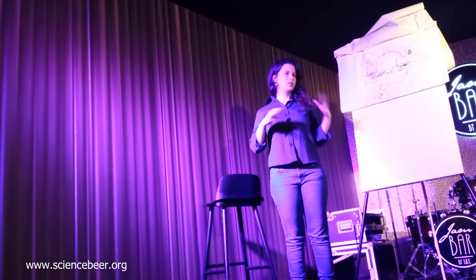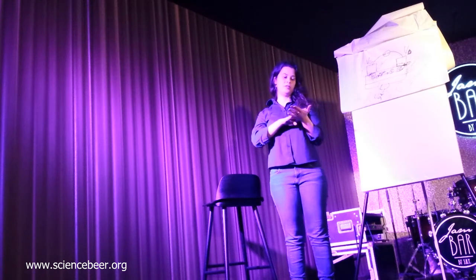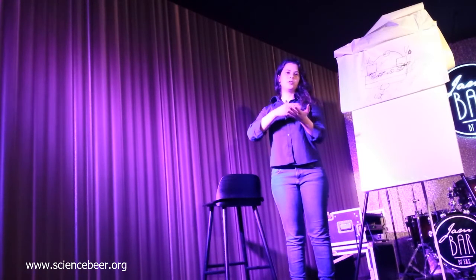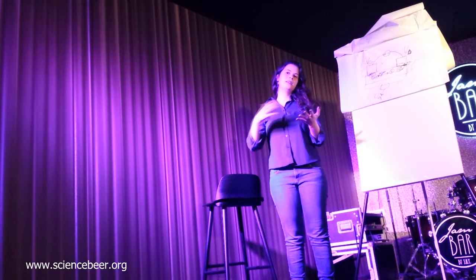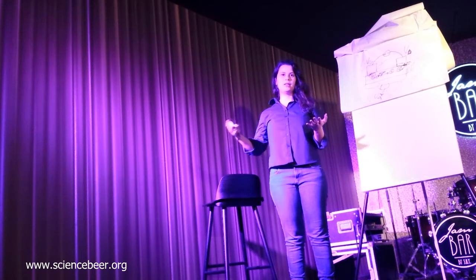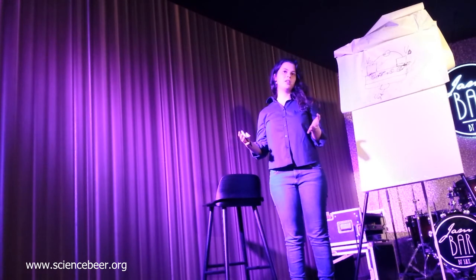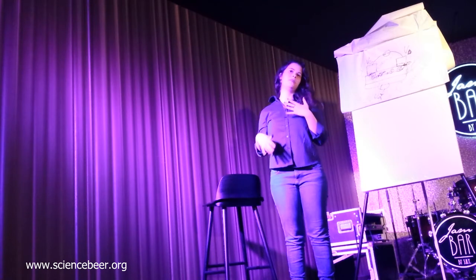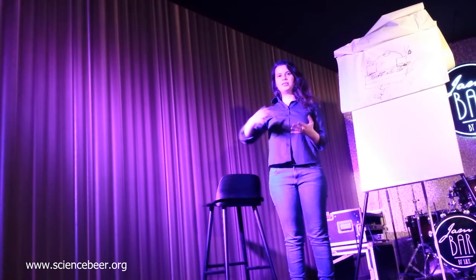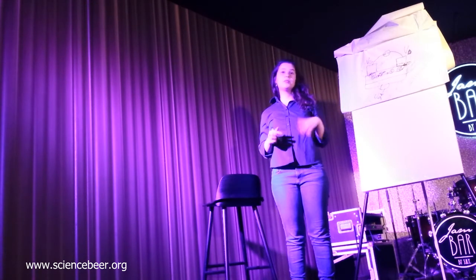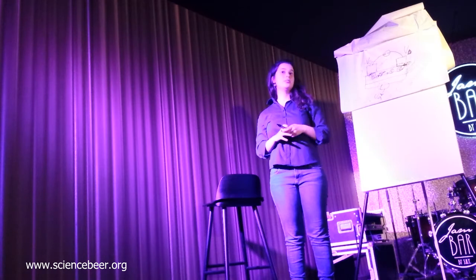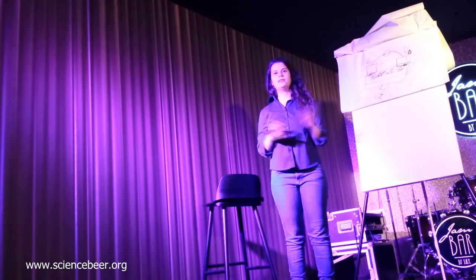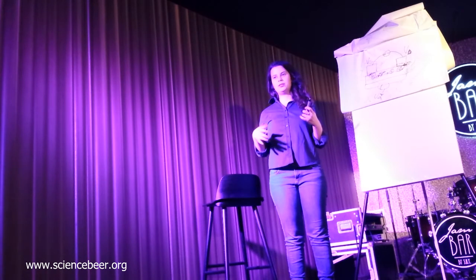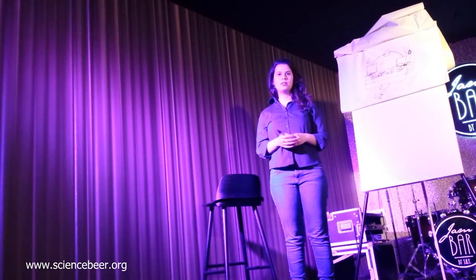Some of them last a few hours, for example, the surface treatment, so you cover them before they go bad. Sometimes the semiconductor is very stable for several days, or sometimes it's stable if you do a certain treatment to it, or if you keep it in a glove box. But all the processing happens in air. Sometimes the measurements are better if you do it under nitrogen.